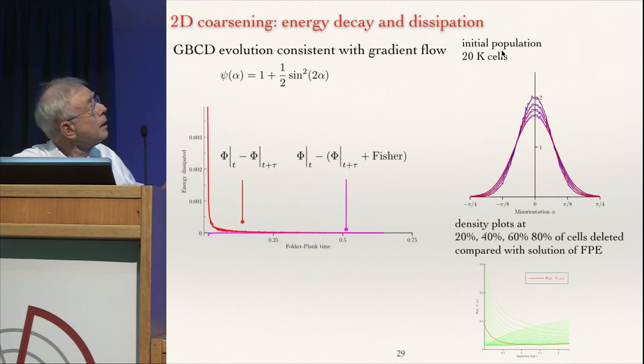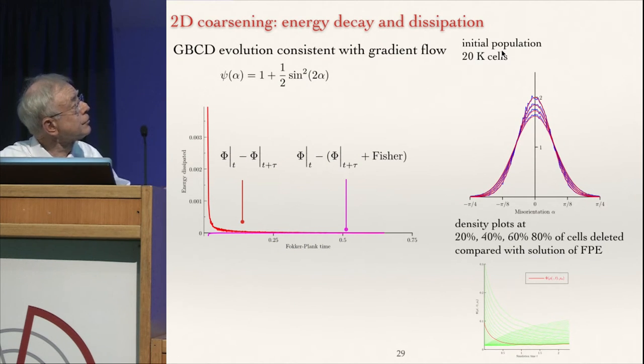So here, this red curve is just the difference in relative entropies at a given time minus the previous time. That's always non-negative. And it moves down, yes. And this is the dissipation relation with the Fisher energy, which you can see is that magenta, and it's almost flat zero. It starts a little bit positive, and it's almost flat zero. And here are the density plots of the solution at 20%, 40%, 60%, and 80% of cells deleted. The simulation was stopped at this time when about 80% were deleted.